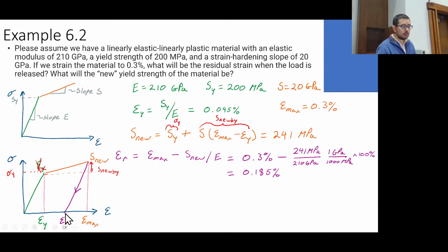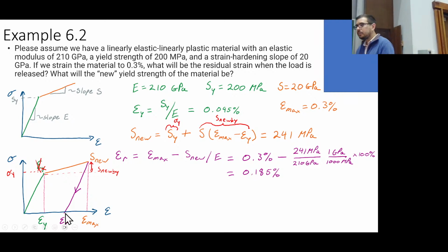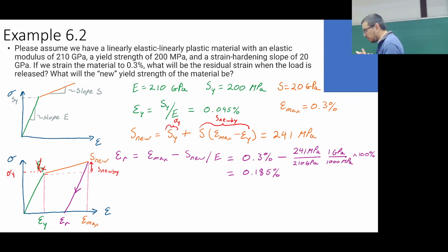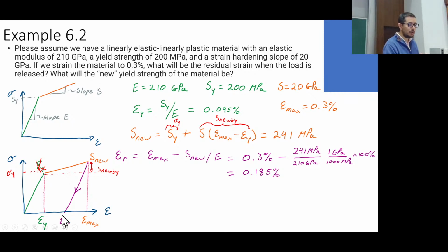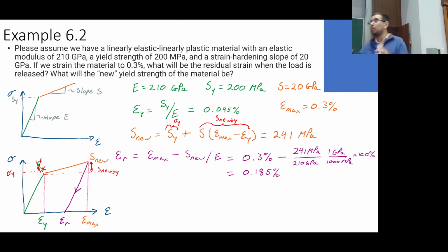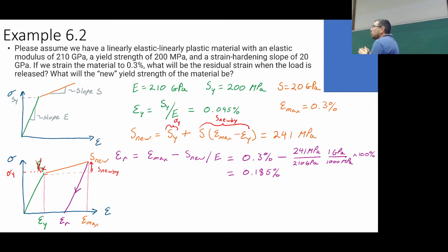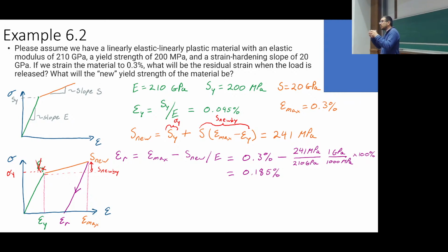When you get back down, you have this residual strain. So I ask you to calculate the residual stress: how much stress is in that material if I'm back down here, at this point? Zero, right? There's zero stress. So there's no residual stress in this case. This is for a nice uniaxially loaded bar. I stretch it, plastically deform it, it goes back just a little bit, and then I let go, and there's no stress. It's just strain.